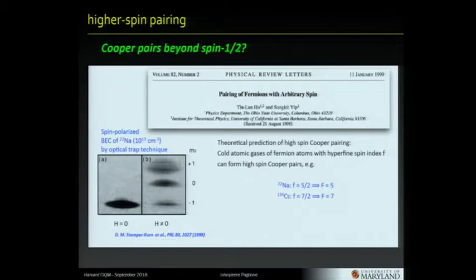Now back to the superconducting state. So this interesting normal state band structure, we know, has strong band inversion, strong spin orbit, and the chemical potential lies right in this gamma 8 band, that's a J equals 3/2 degenerate band. J equals 3/2 in essence means you have electrons, or quasi-particles I should say, with spin 1/2 up and down and spin 3/2 up and down, right?